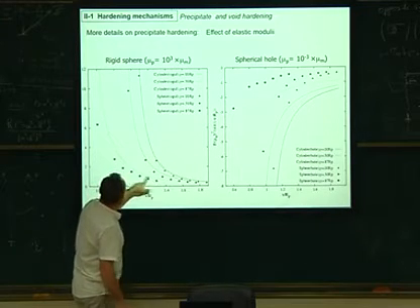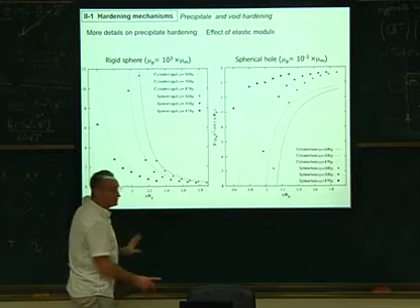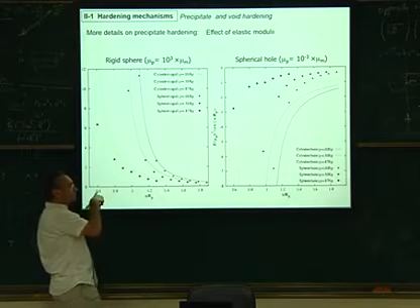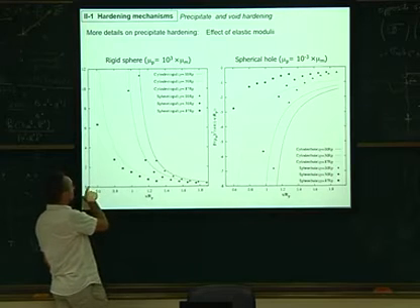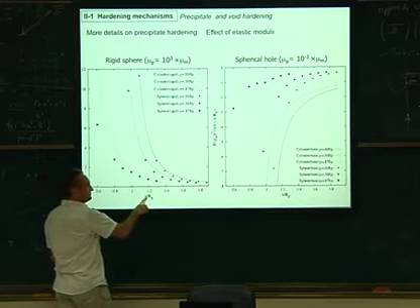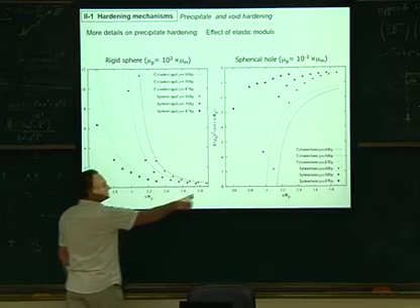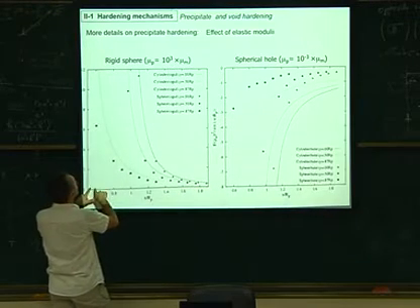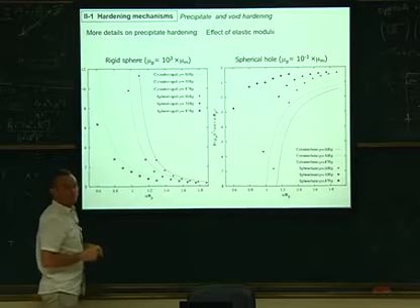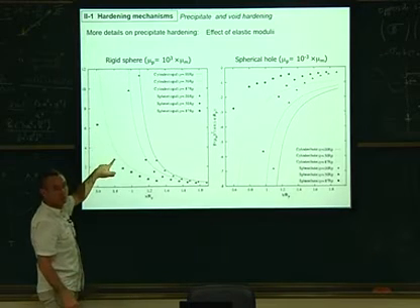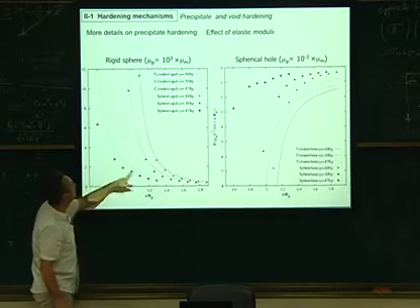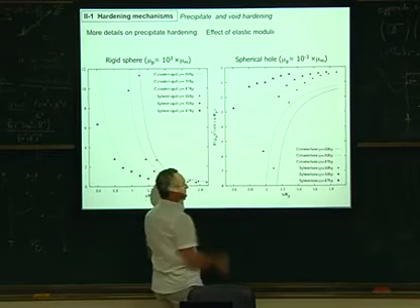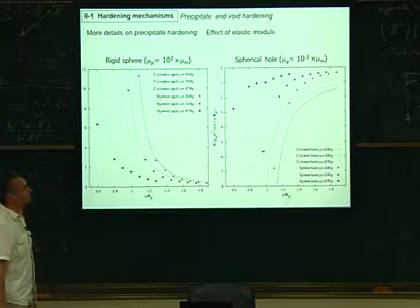So what did I plot here? First, I should explain what I plot. Here I plot the force back on my dislocation when it is closer to the particle. The particle is here, at 0. This is the position compared to the particle radius. So here I am far away from the particle, and here I put my dislocation closer and closer. And the closer I am, the higher the force. So it's a repelling force from the particle. You can see how it behaves for the sphere compared to the cylinder. And the same for a void, how it attracts the dislocation more easily depending on the position.